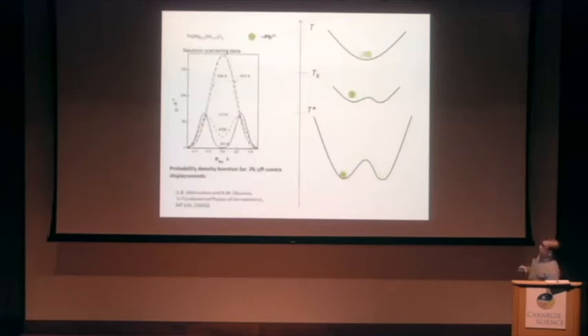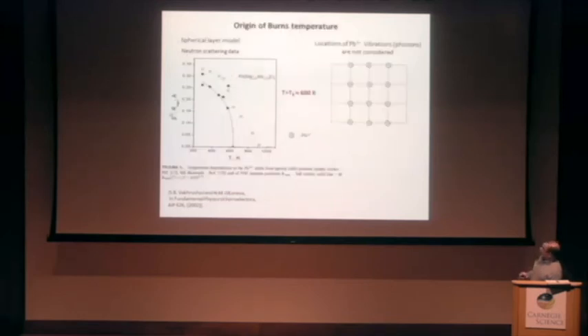And interestingly, this picture corresponds exactly to the probability density function found some time ago by our chairman in PMN when he studied neutron scattering. And this is the distribution of lead ions. The maximum of the probability density function corresponds to the minimum of the potential. Thus, again, in the figure from the paper, the shifts of lead ions from the centrosymmetric position vanish at the Burns temperature, and it looks like a phase transition.